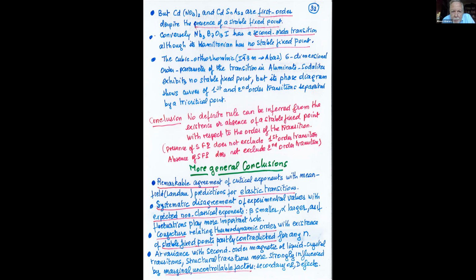So my attitude would be that the fluctuations in this material are probably relatively weak, and therefore to see the crossing to a first order transition, you have to go very, very close to the transition. In all your tables, you had a temperature range of the order of 10 to the -1, that's much too large for seeing real critical phenomena.